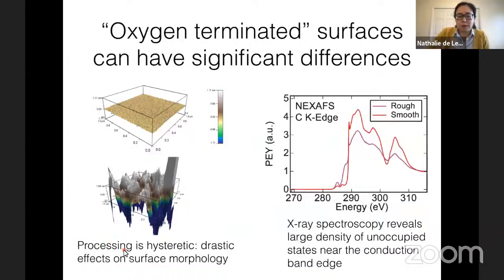And the real problem here is that processing in diamond tends to be very hysteretic. So if you do some oxygen processing, what happens is you have an enormous etch rate anisotropy of different crystal facets in your diamond. So that means that if you start with, say, two substrates that have just very slightly different surface roughness, and then you put them through the exact same process, you can end up with, this surface stayed pretty smooth, and this surface has this kind of crazy surface roughness at the end. And we could see direct consequences to the electronic structure of this kind of surface morphology.